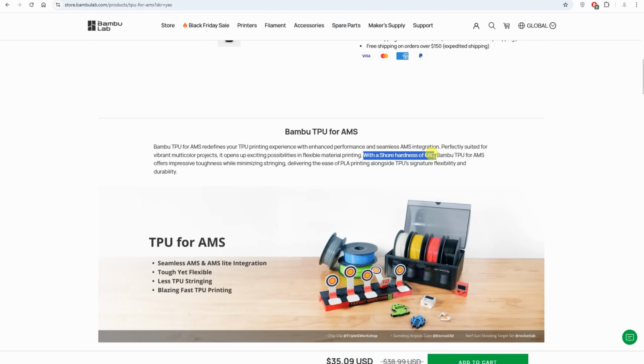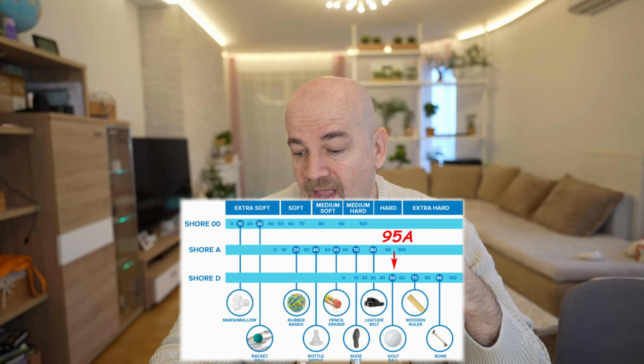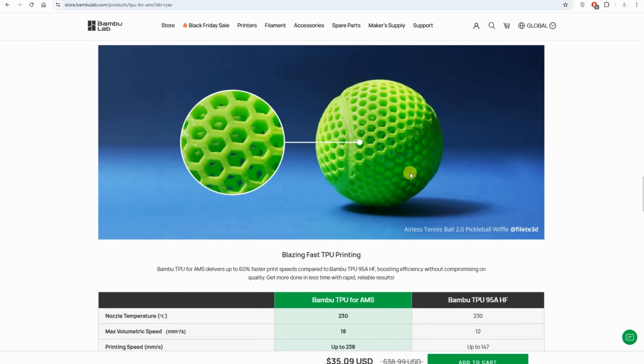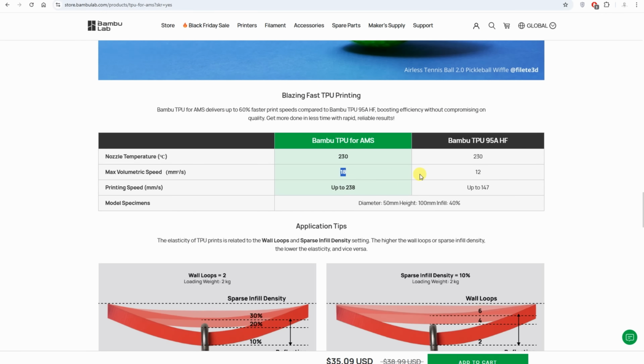And about the hardness, the previous one has the hardness of 95A on Shore scale, but this one is not even measurable on Shore A scale. It has a hardness of 68D on Shore D scale. Just for comparison, the 95A would be approximately 50 on Shore D scale. And with this we can have fast printing, because the maximum flow rate is 18 cubic millimeters per second, and just for comparison, the TPU 95A HF has a maximum flow rate of 12, and the previous TPU by BambuLab had a maximum flow rate of 3.6 cubic millimeters per second. So huge difference, and with this we can have really fast printing.